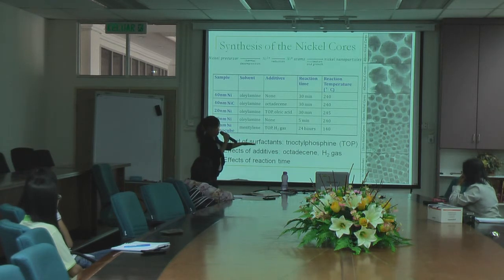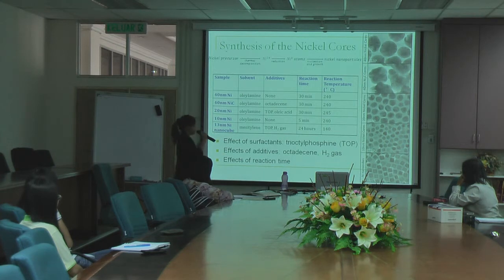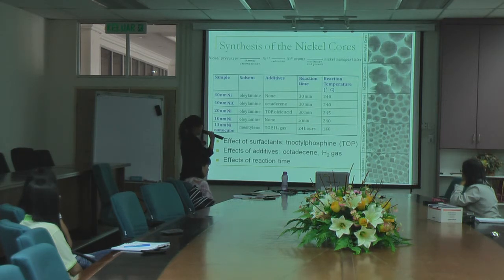And then the second reason, based on my understanding, is that the growth of these particles, actually they grow better when they grow slowly. When the growth is too fast, there's a preference to form the most stable shape, which is the spherical shape. So when the growth is very, very slow, other things such as the hydrogen gas can have a more dominant effect on controlling the shape of the particles.